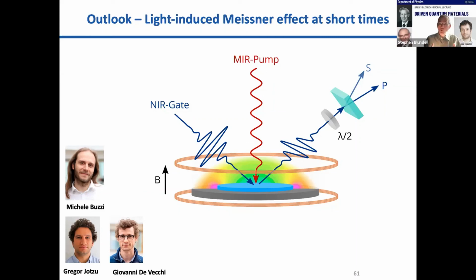Yes. What size of magnetic field can you apply in your setup? Because I was also thinking not only on the superconductivity, but your beautiful measurement where you measure the interatomic potential. It would be very nice to see how in certain non-superconducting materials, those that show magnetostriction or interesting magnetostructural coupling, whether you could measure those kinds of curves in high field. Okay, two answers. Answer number one, in the specific case of the superconductor, we are trying to apply a field in the Meissner regime, which in these materials is a millitesla. So as small as we can get away with.